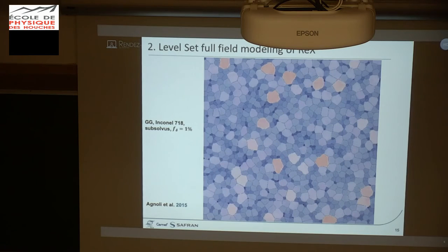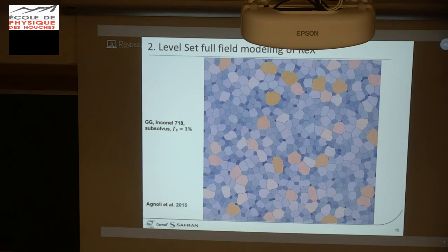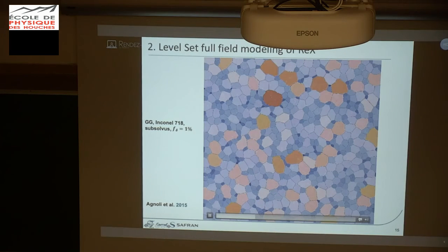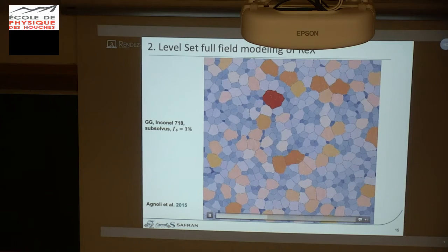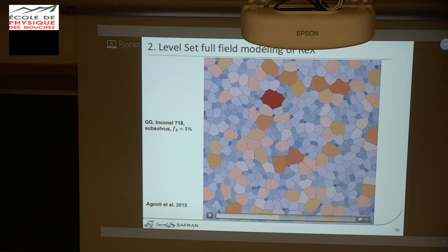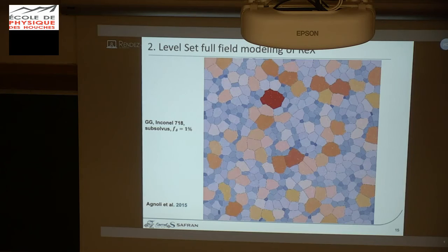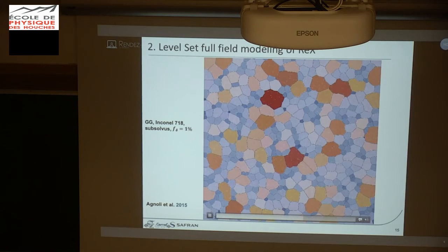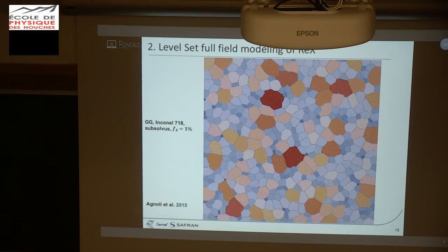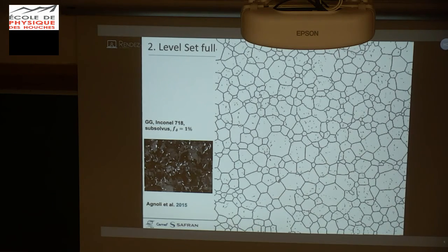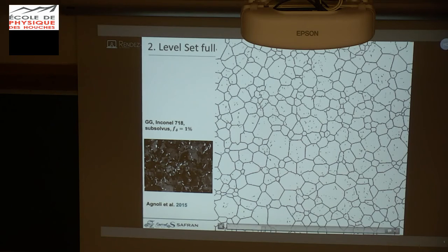And now I'm going to show you an industrial example of this kind of simulation for Inconel 718. On the right, maybe it's difficult for you to see, the points are second phase particles immersed in the finite element mesh. It's a classical thermal treatment with a given density of the second phase particle, delta phase here. You can see that at one moment you really obtain a pinned microstructure due to the presence of second phase particles, a static microstructure. And here, of course, we are in subsolvus condition, and we don't have evolution of the second phase particles.